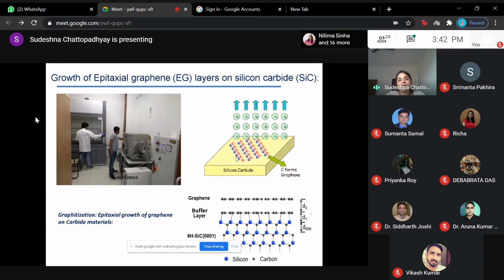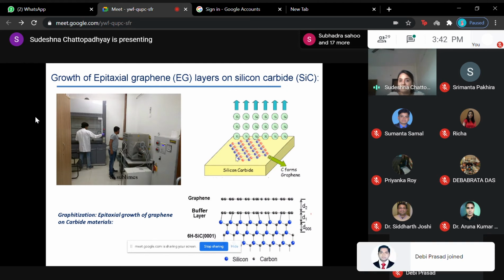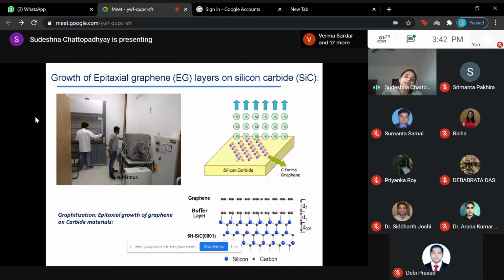Many experiments don't matter with a smaller sample size, maybe 5 by 5 millimeter or 10 by 10 millimeter is good enough. But for many practical uses, a bigger sample size is required because of large scale deposition. For application purposes, an ultra high vacuum system is always a limitation because it is expensive, and second, you are restricted to a smaller sample size. So for ambient pressure graphitization, it would be a good process, with high temperature more than 1700 degrees centigrade at ambient pressure, with inert gas, because we don't want contamination from the present gases.